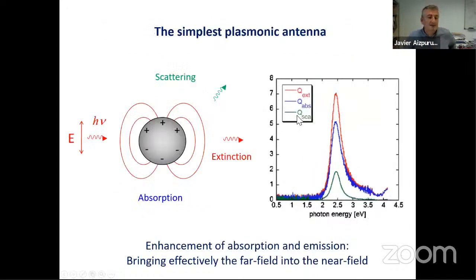And we can see that this is a special cavity or resonator with very standard optical spectroscopy in absorption or in scattering, right? Most of you might be familiar with this. We come with light of a certain frequency on a metallic nanoparticle, and we can put a detector in transmission or in scattering and measure the scattering or the absorption cross sections that peak at a particular photon energy or light frequency, which connects with the oscillation of the conduction electrons, which we call this quasi-particle or plasmon. So this plasmon, this condensed matter excitation, is the key to make the transfer between the propagating photon to a trapped plasmon polariton.